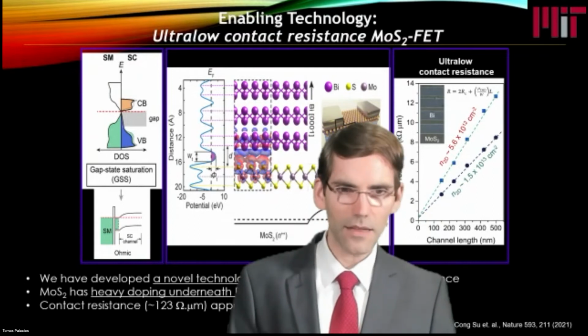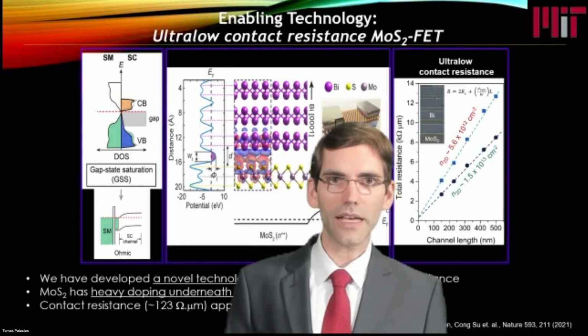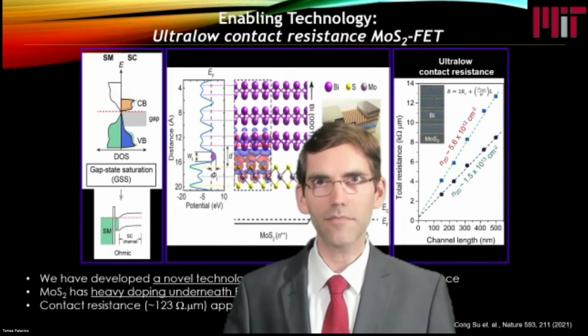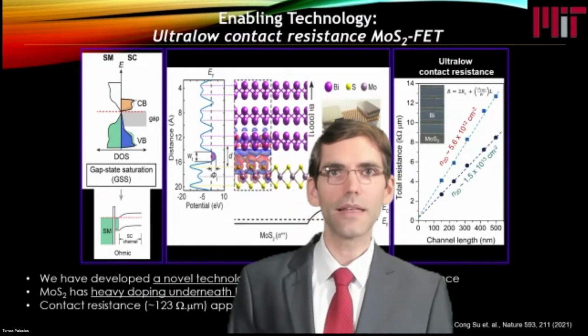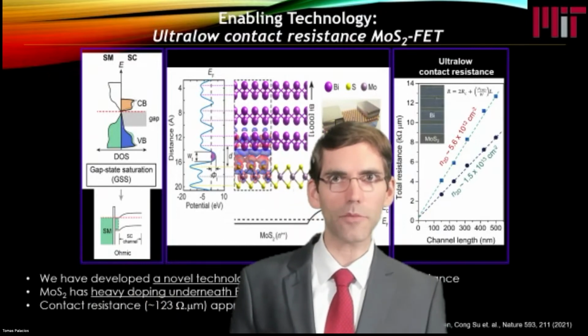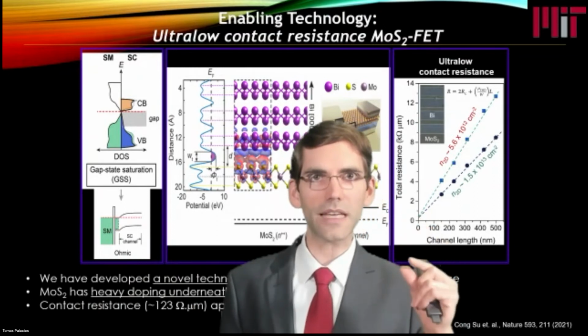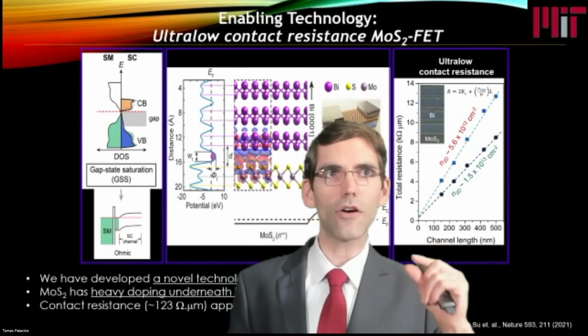To fix that, we decided to use a semi-metal rather than a metal, in this case, bismuth. The advantage of a semi-metal like bismuth is that the density of states is going to be very, very low.